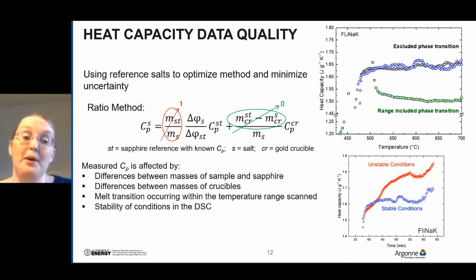The figure on the top indicates why excluding the melt transition from your scanned temperature range when you're measuring heat capacity is so important. You can see in the green squares that we started at around 420 and scanned right through the melting point of FLiNaK, and that resulted in a depressed heat capacity value. Whereas with the blue circles and dark blue circles, we started above the melting point with a nice homogeneous molten salt, and we obtained a nice flat response, which was not depressed.